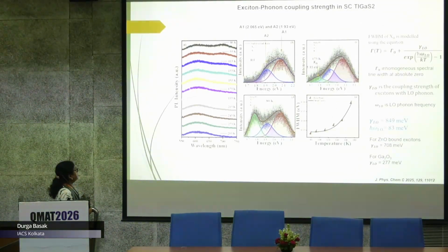Next, we have compared the photoluminescence of this material as a function of temperature, and we have deconvoluted this broad peak into 2 peaks at room temperature, which are termed A1 and A2. But when we go to lower temperature, another peak arises, which is due to the bound exciton XB. And if the temperature is further decreased to 80 Kelvin, this peak becomes intense and comparable to A1 and A2. So we have found the FWHM of this bound excitonic peak at all the temperatures and fitted following this equation. And this gamma optical is giving you the coupling strength of the exciton with optical phonons.